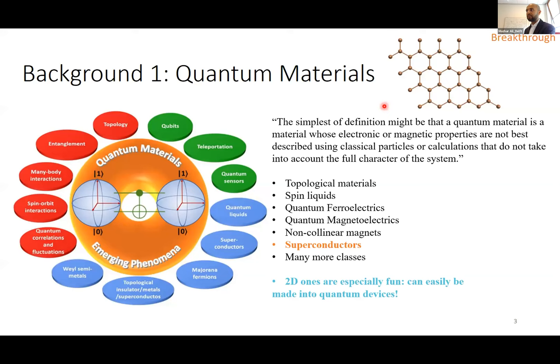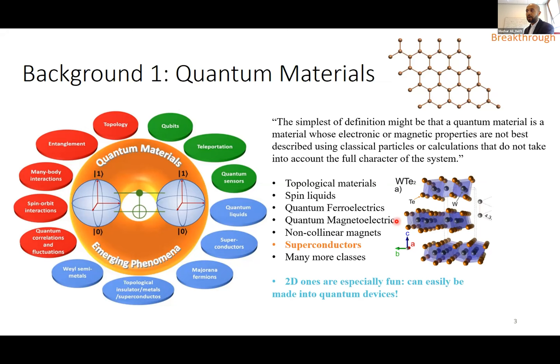Some more examples of these quantum materials: of course there's graphene. One very near and dear to my heart is tungsten ditelluride, which has sheets of a pseudo-hexagonal lattice of tungsten coordinated octahedrally in a deformed octahedra by tellurium. And since we're talking about superconductors, the famous 1-2-3 superconductor YBCO is a rather layered material, with the copper oxide square planes being very important for that superconducting property.